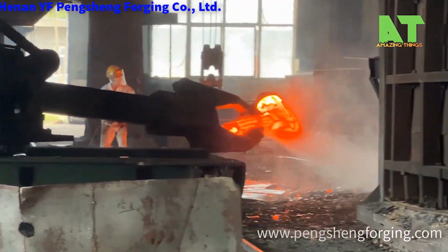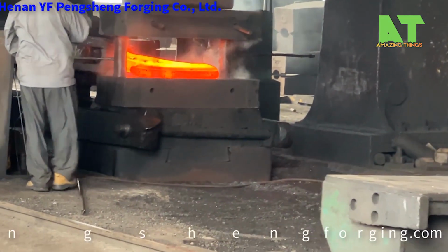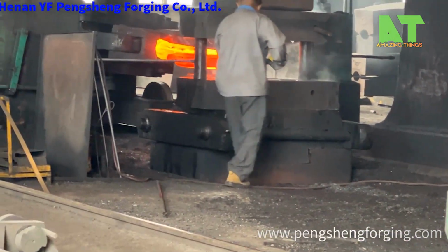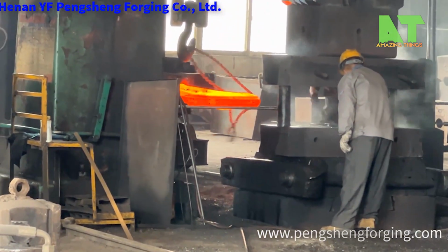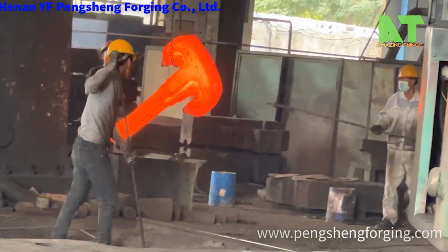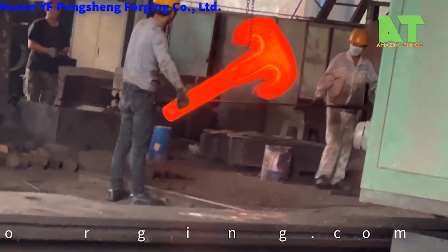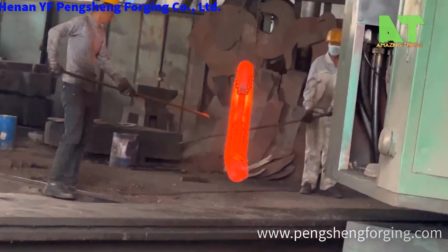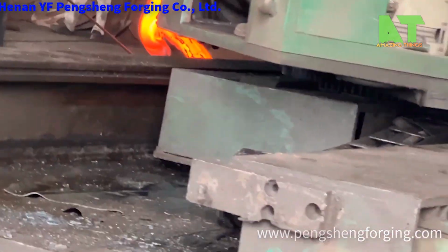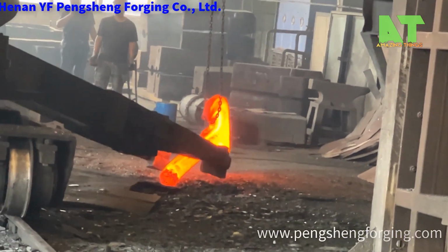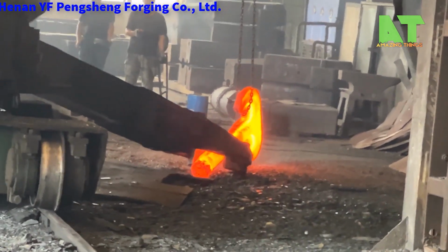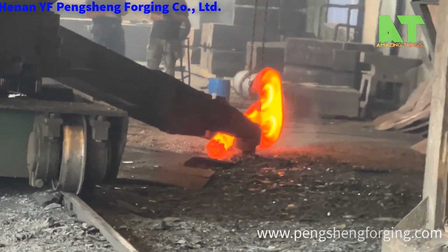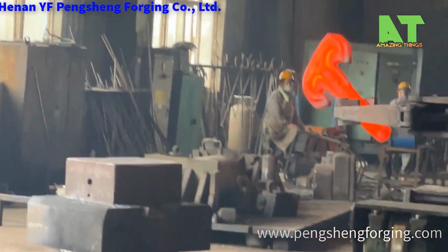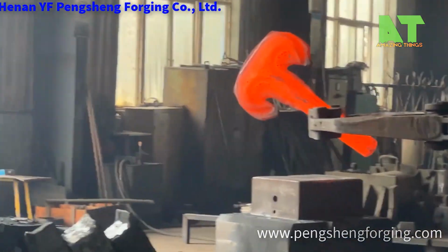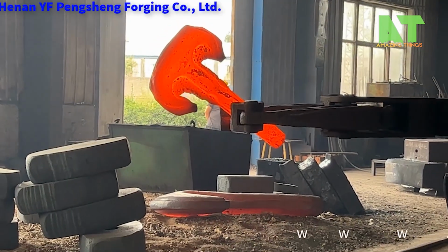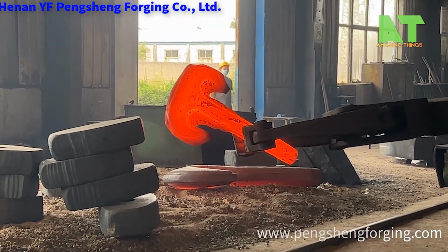The billets are then transferred immediately to the forging press. The forging press slams down with thousands of tons of force, shaping the red-hot steel into a near-net hook form. Multiple die strikes are used to gradually form the hook's shape, ensuring the grain structure of the steel flows along the contour of the hook, not cut across it. That's critical for strength. After forging, the hook goes through a controlled heat treatment process, normalizing and quenching, to refine its grain structure and achieve the required mechanical properties like tensile strength and impact resistance.